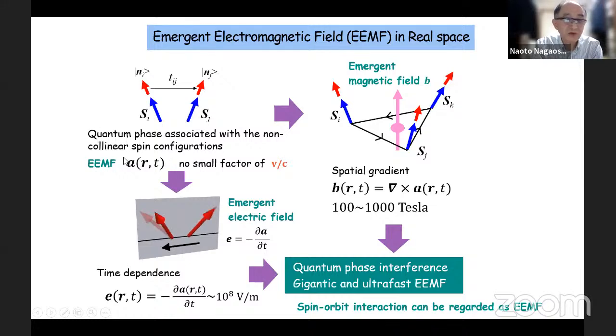Then usually this vector potential for the Maxwell electromagnetic field is weakly coupled to the electron compared with the scalar potential. But for this spin electromagnetic, so-called emergent electromagnetic field case, you have a rather strong coupling. For example, this strong coupling leads to a very large effective magnetic field once you have this non-collinear spin structure with a solid angle. Then this leads to a huge magnetic flux, small b, which corresponds to, let's say, 1,000 Tesla, once the spatial scale of the spin texture is nanometers.